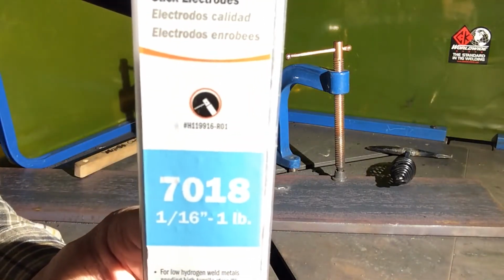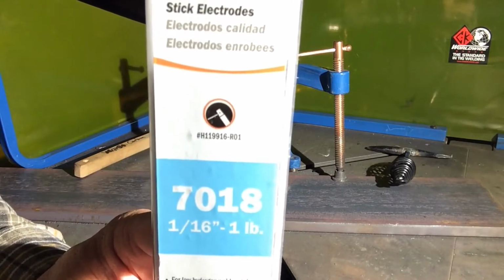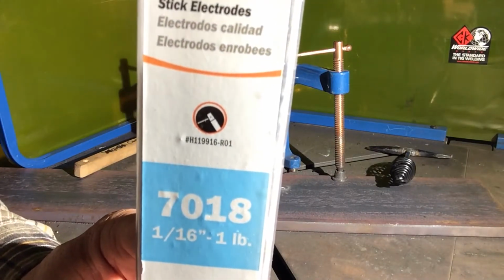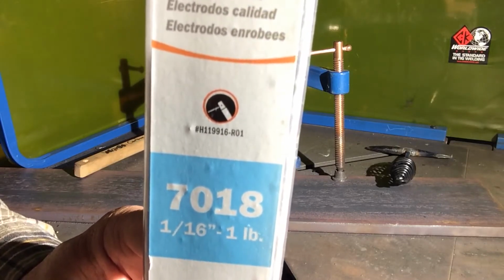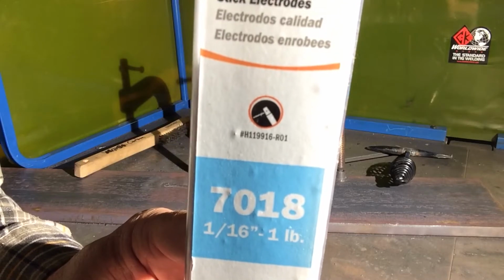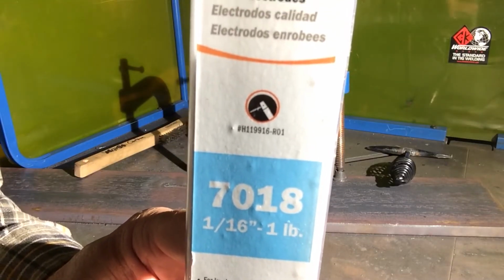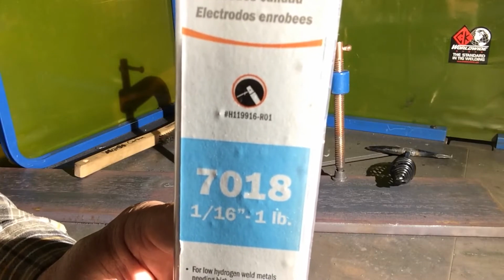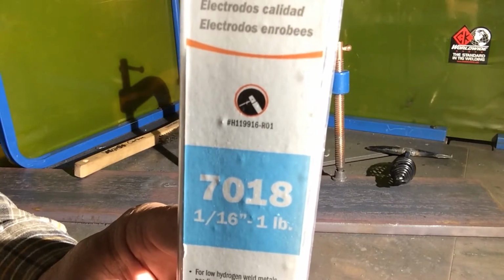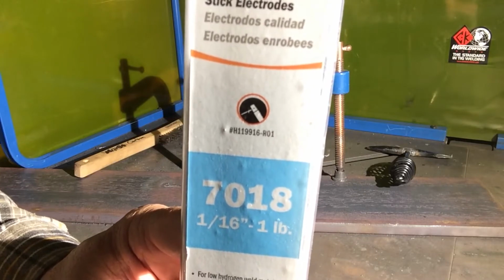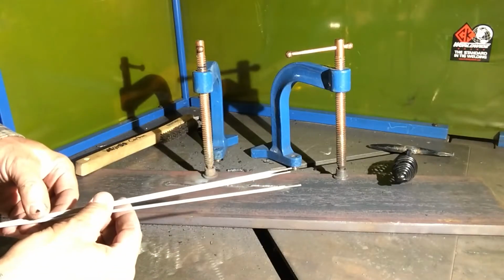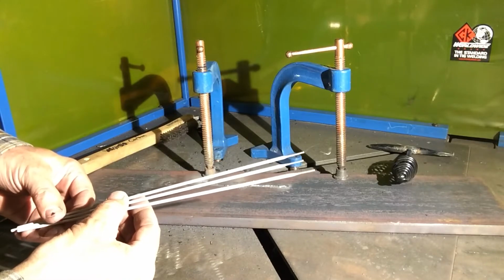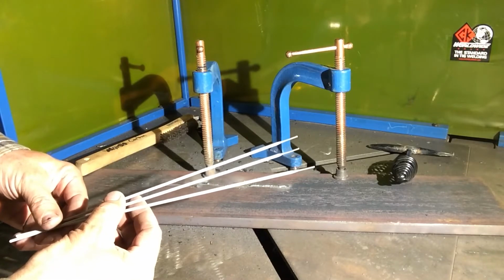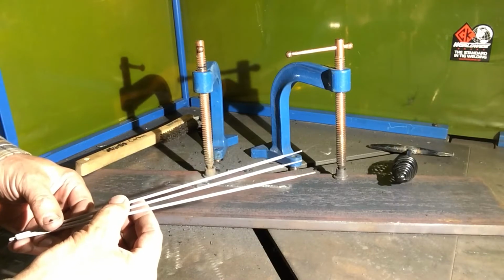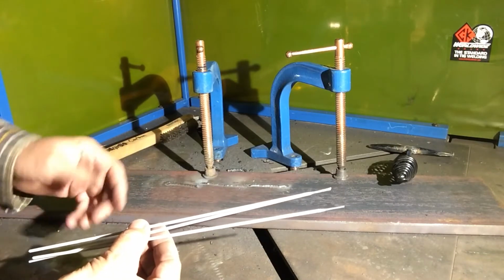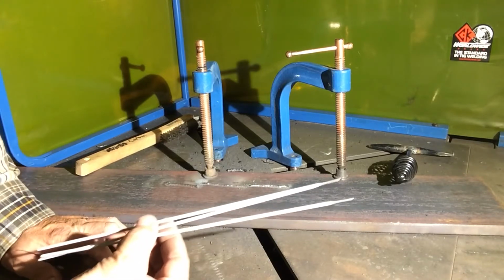I bought a pound of this. It's 1/16. It did not say on the package how much amperage to run, and I Googled it, and it said for 7018 you want to run about 30 amps for every 32nd inch. So 1/16 is 2 32nds, so that'll be 2 times 30 amps, so I'm going to try 60 amps DC electrode positive. I remember that when I had the 7014s in 1/16 inch, the package said to run it between 35 and 60 amps. So now I said 60 amps maximum for the 7018.